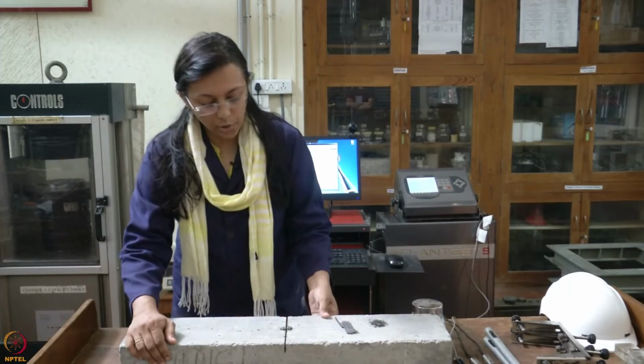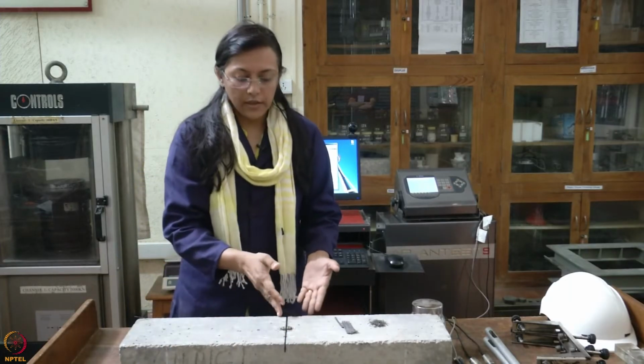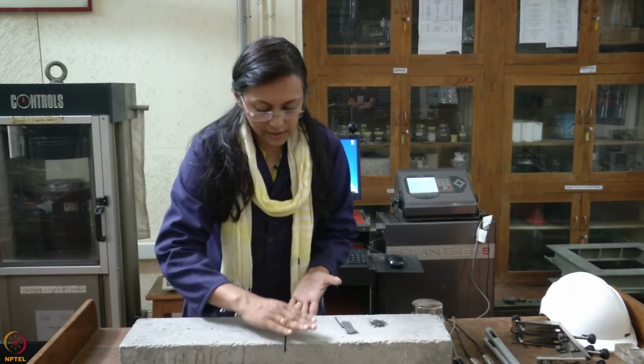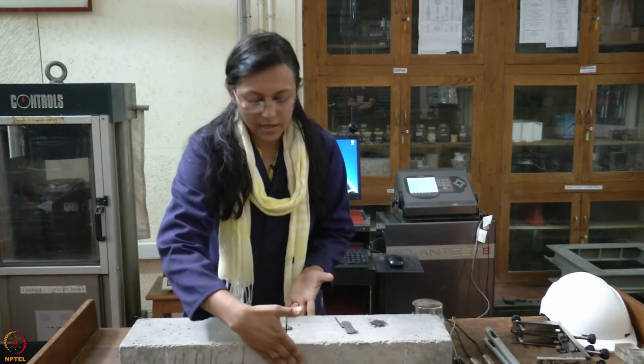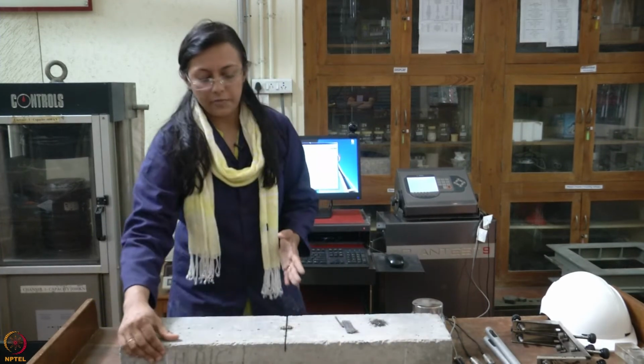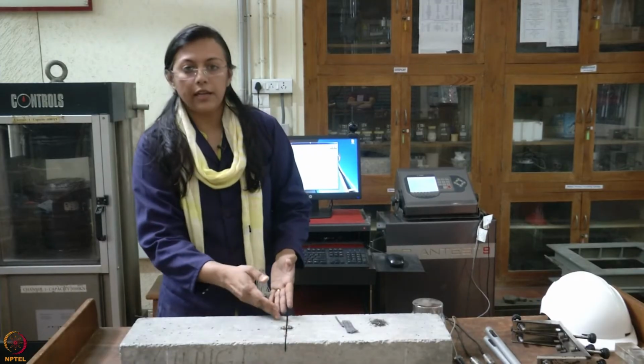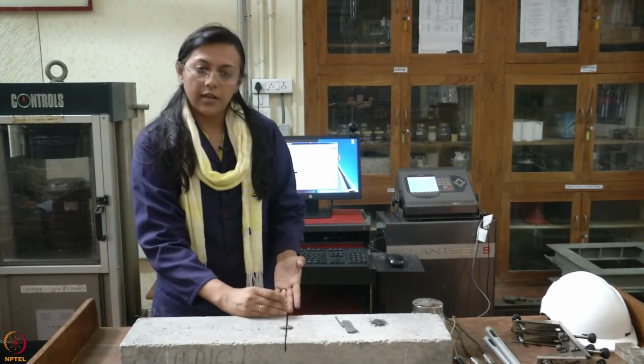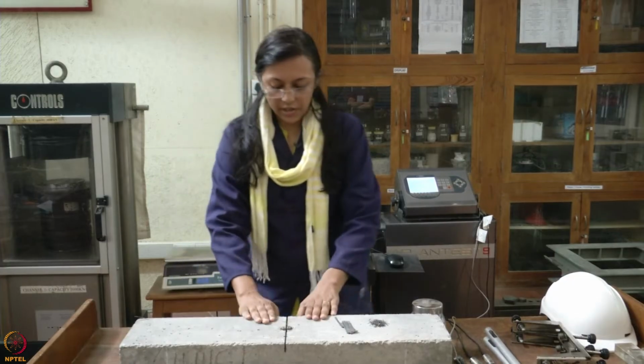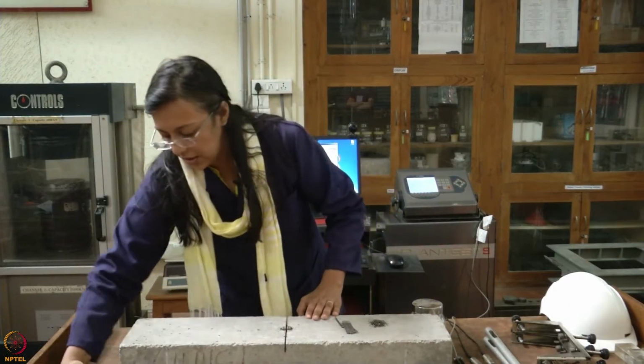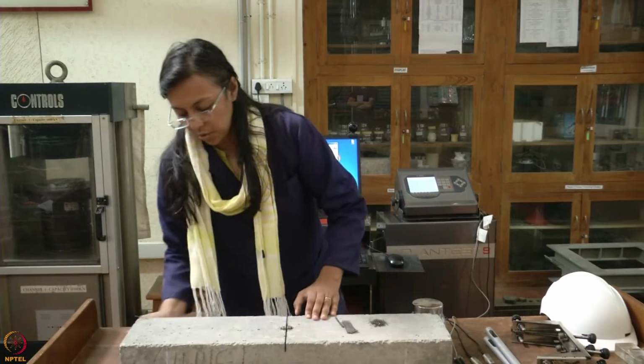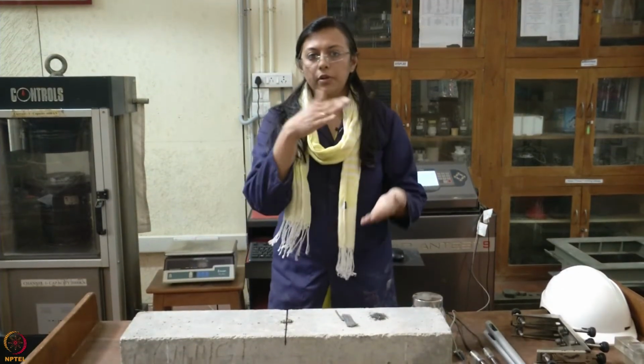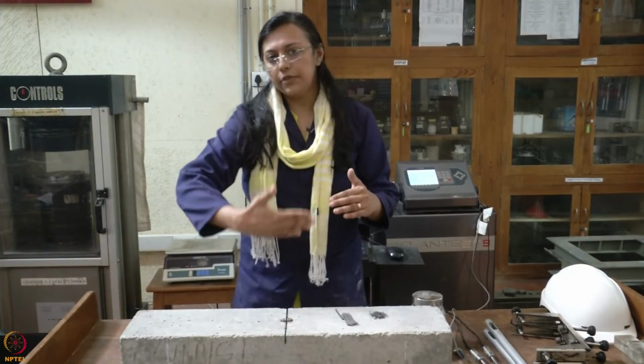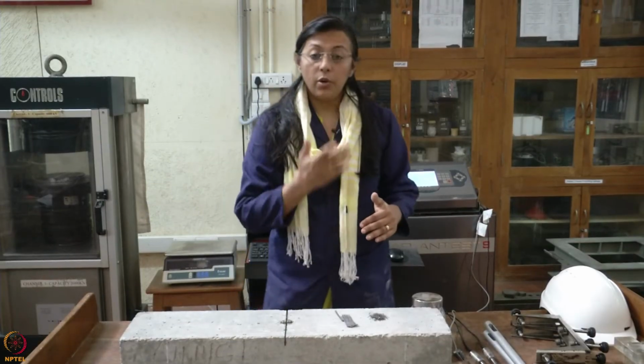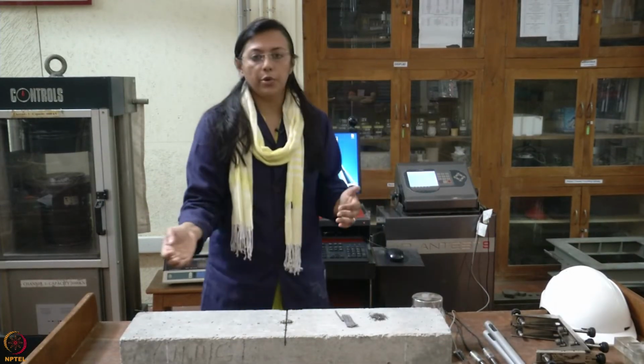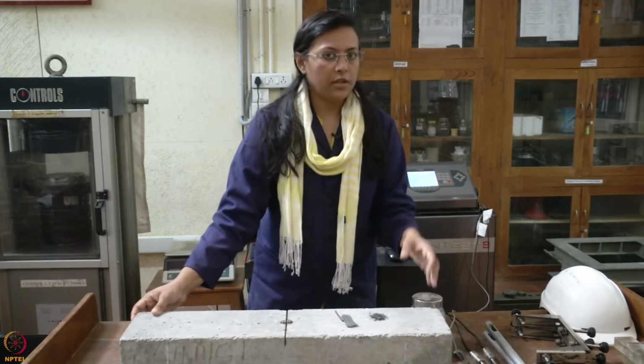One more important thing to be noticed is that the notch is cut at the mid width in the direction perpendicular to the casting face. This is the casting face of the specimen, and the notch is cut in a direction perpendicular to the casting surface, and the loading direction is also perpendicular to the casting face. So loading on top, notch on the bottom, and casting perpendicular to it. Now let's see how we are going to mount the specimen onto the testing frame.